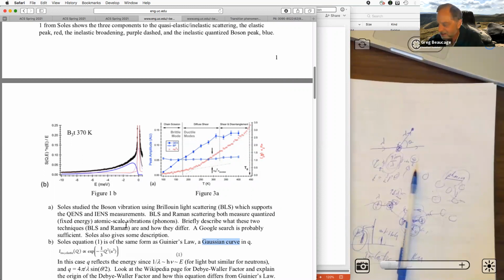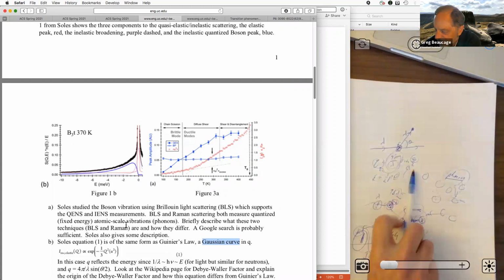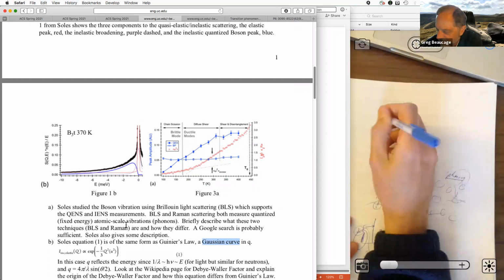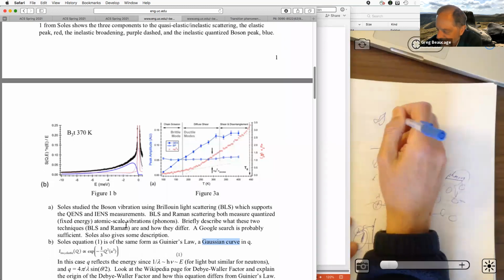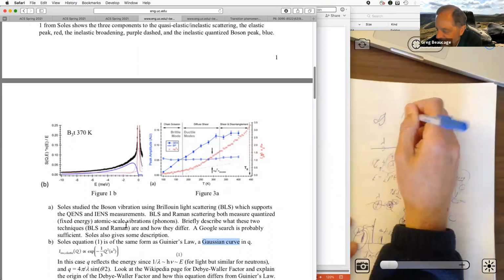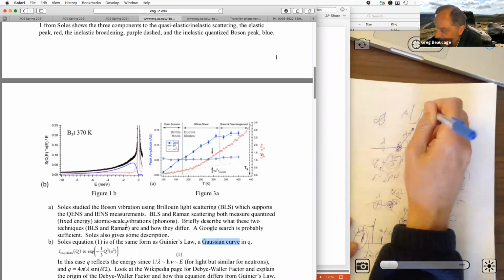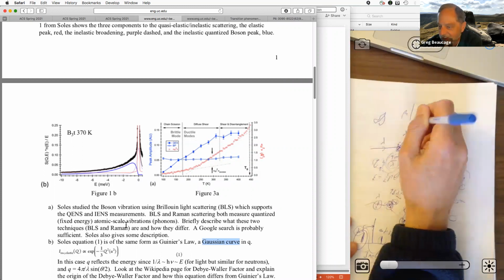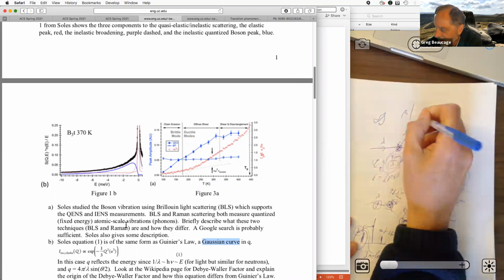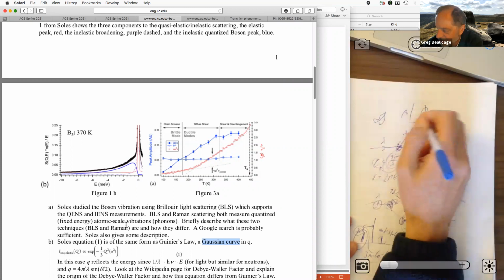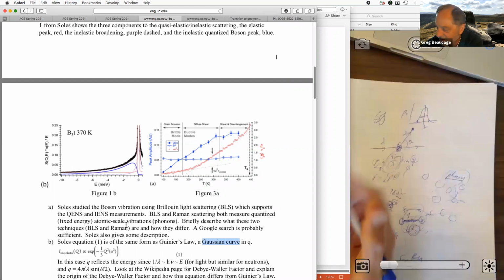In the case of Guinier's law, you're talking about a structure, some odd structure, and if it's isotropically moving around, then the electron density of that thing looks Gaussian, except it has a fixed size, so it truncates, right? So you can model that broadening of the electron density as a function of size due to thermal motion of a randomly shaped object, or it could be a polymer coil.